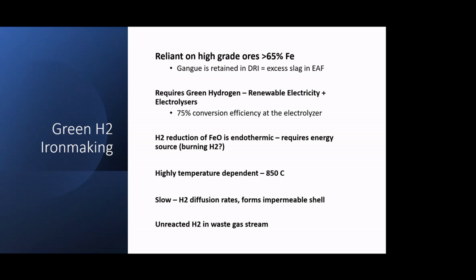The other thing about hydrogen is that if it's going to be green, it requires renewable electricity, and the conversion efficiency at the electrolyzer is at best 75%. So it's a large consumer of electricity. And as I said before, hydrogen reduction of iron is endothermic, so the pellets have to be heated and the gas has to be heated before it even enters the shaft furnace. It's also very highly temperature dependent, and if the temperature varies, you get problems of low reduction rates, sticking of the iron to the shaft furnace, and the hydrogen can reduce the outside of the particles and stop any more hydrogen from diffusing in.